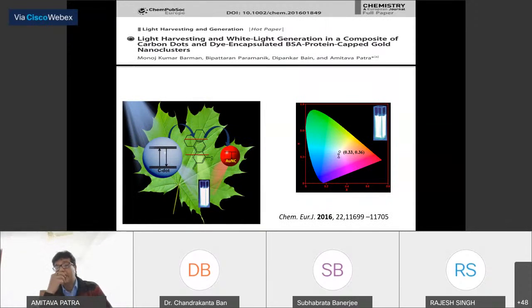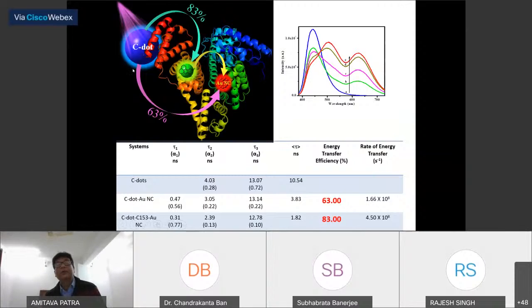And finally, the last slide is the light harvesting system we developed by combining the carbon dot and gold cluster. You can tune the white light. White light generation is a very important topic nowadays, by changing your composition. So what happens here is, if you add the carbon dot to the gold cluster, an energy transfer takes place from the carbon dot to the gold cluster, but that is only 63%. To enhance the energy transfer process, we add a bridging molecule to couple the carbon dot and gold cluster. In that case, we have a cascade kind of energy transfer in the presence of protein molecule. This is the BSA protein.